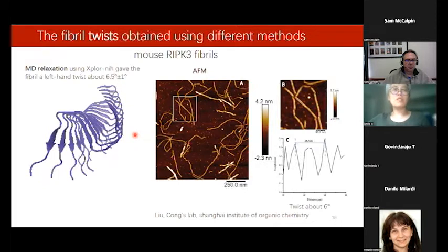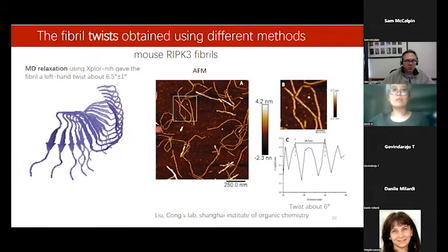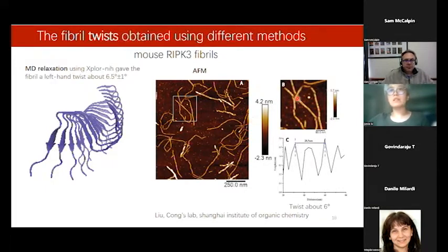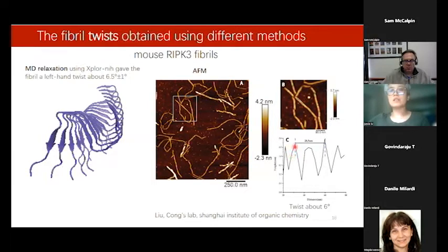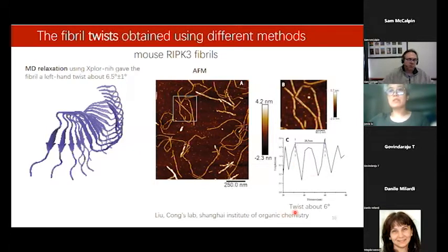The MD simulation also shows the homo-oligomer develops a slight left-handed twist, which is typical for stable fiber structures. While solid-state NMR cannot detect this twist, AFM imaging with Dr. Liu Chong's help revealed periodic height changes along the fiber axis. From these height differences, we calculated a twist of about 6 degrees between neighboring peptides — consistent with our MD simulation results.